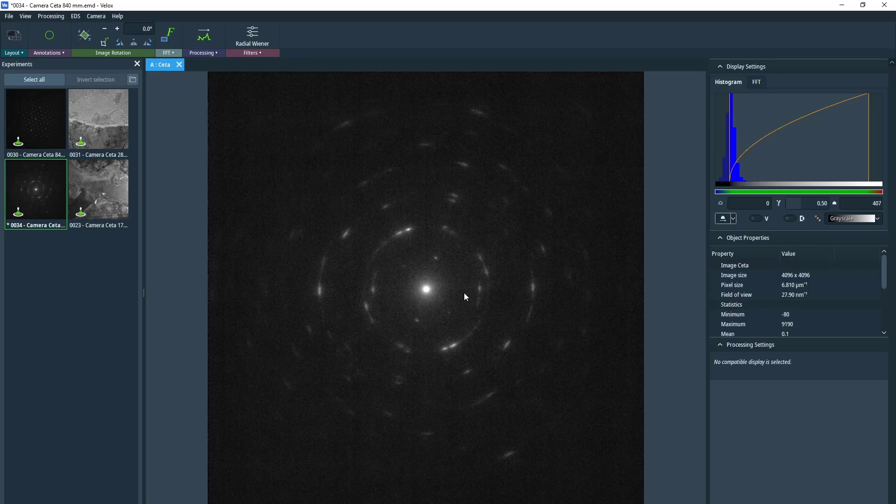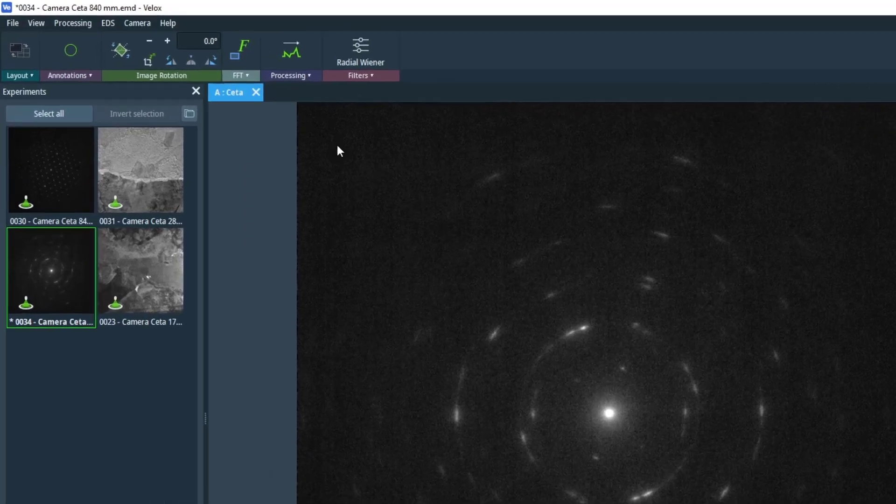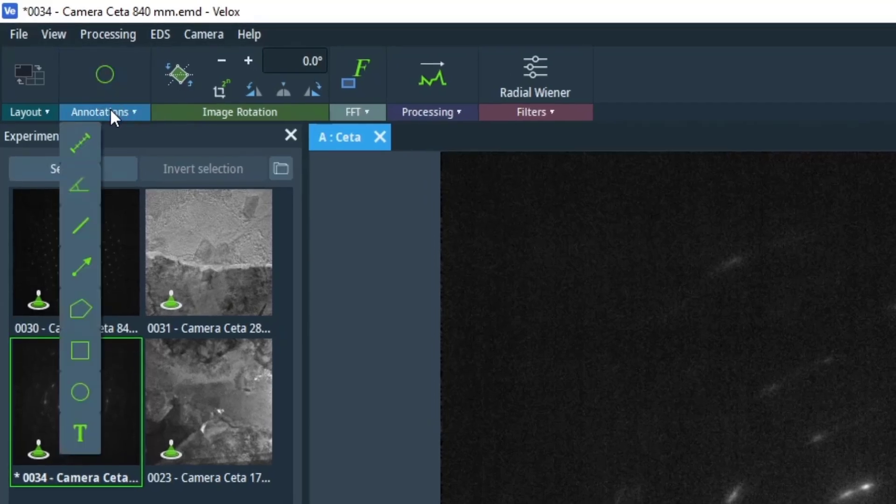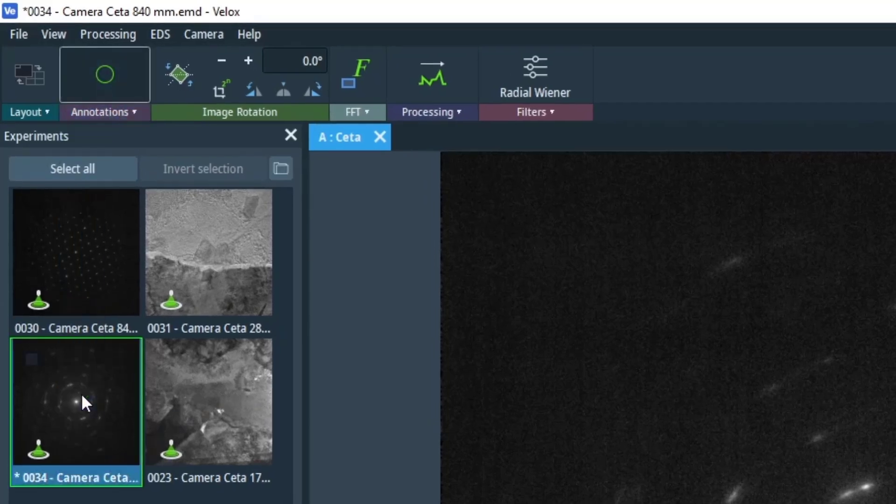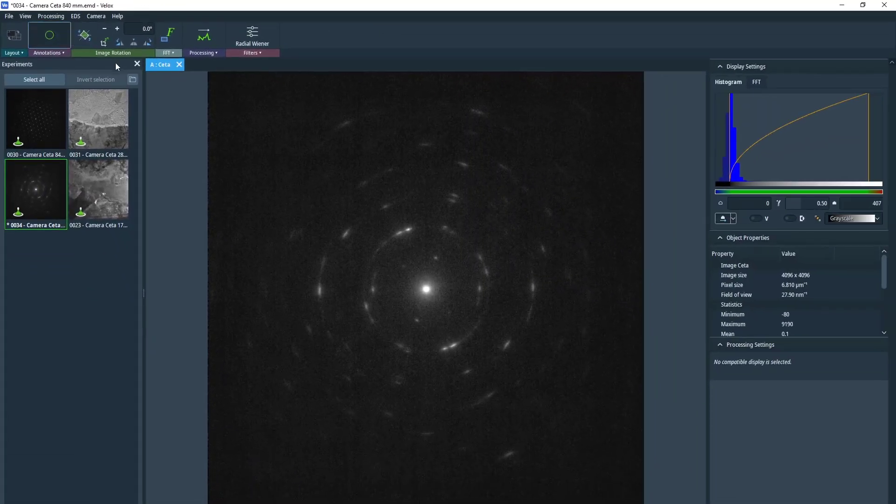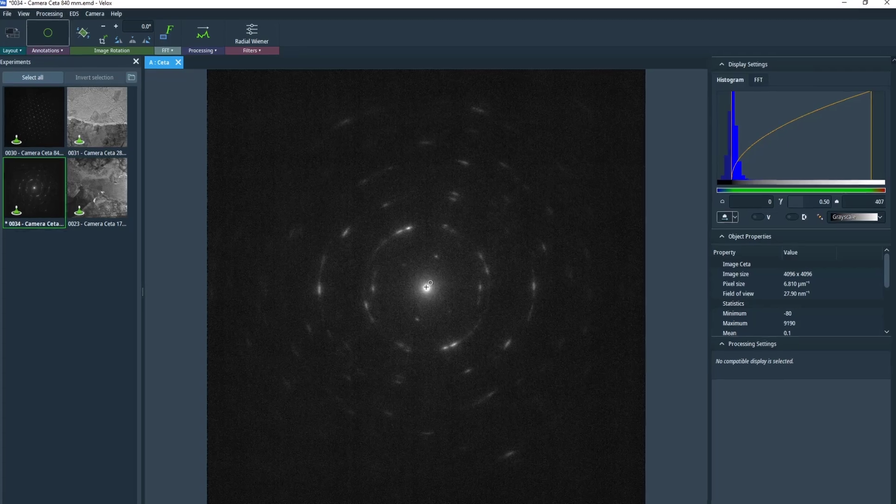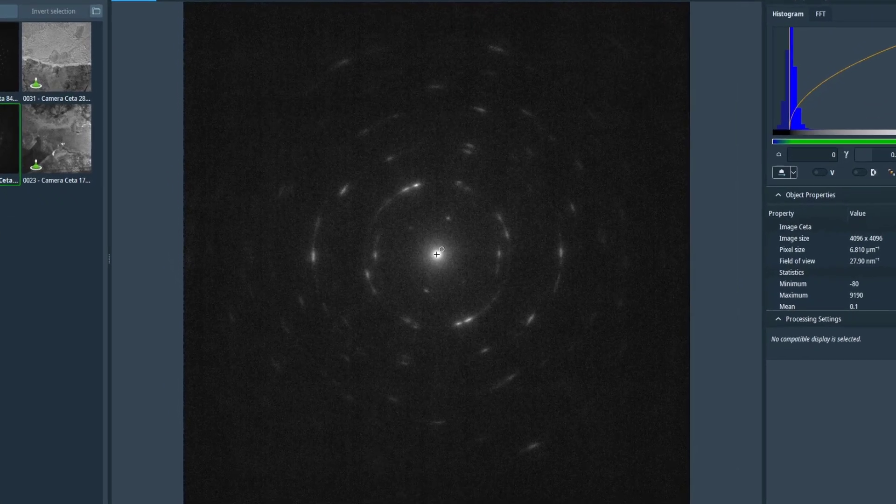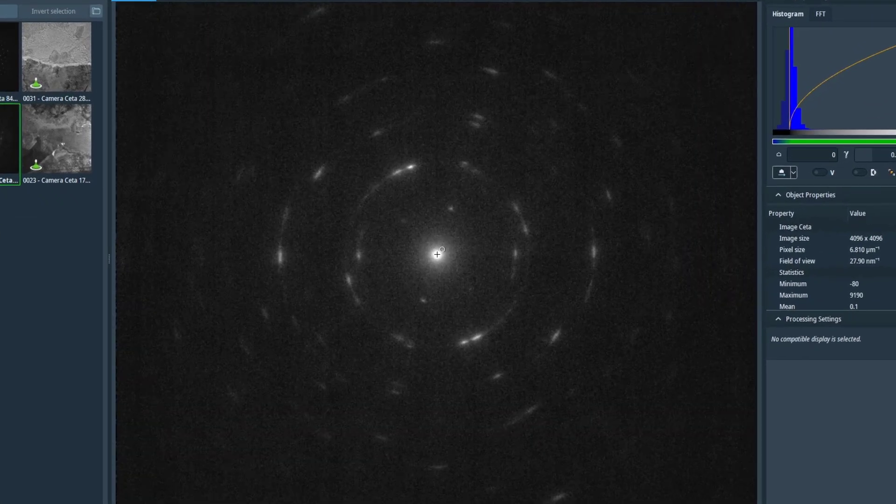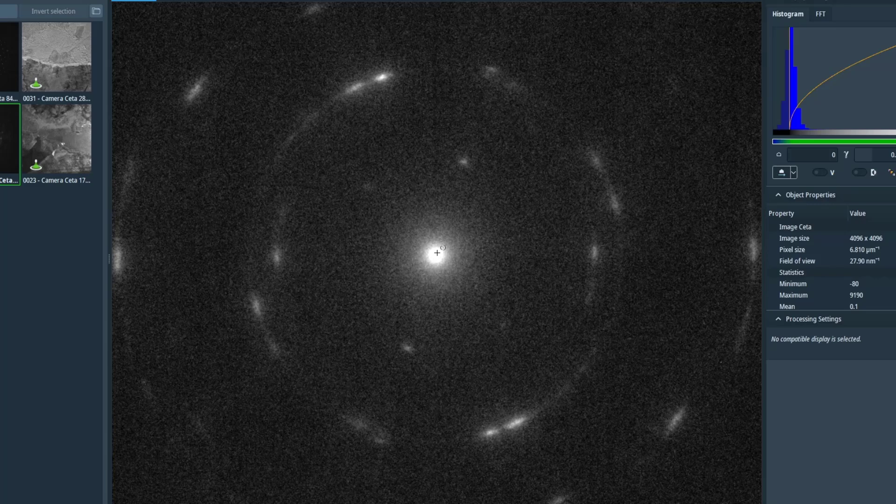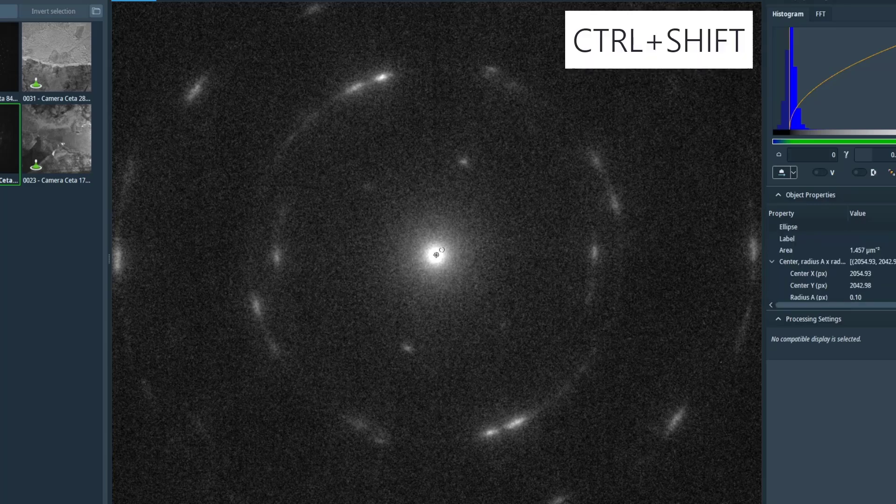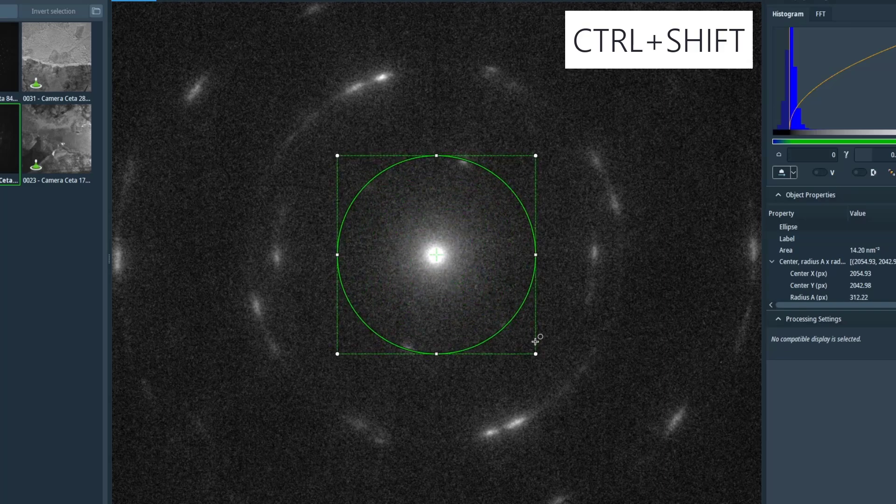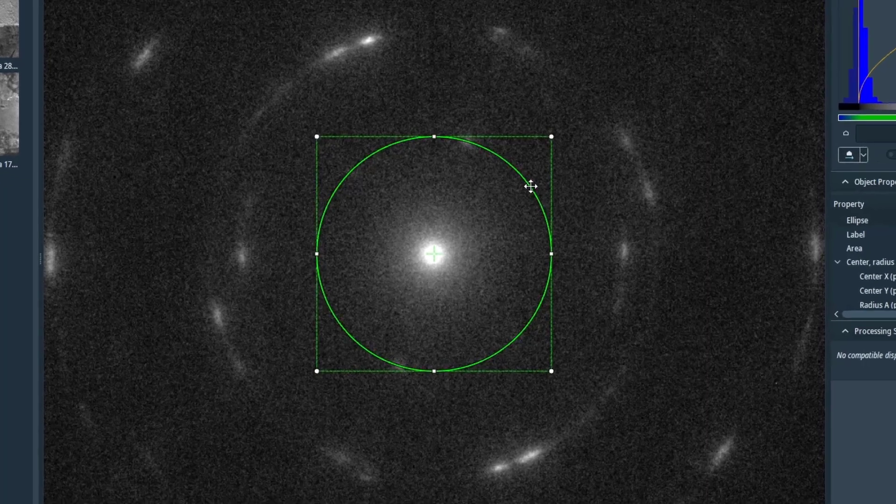Here is our ring pattern that we'll be using. The way that I like to do this is to use the circle annotation in VELOX and then measure what the radius of the circle is, because this is more accurate than doing measurements from the central spot out to these other spots. We want to try to center ourselves by zooming and using the scroll, and then if we hold Ctrl and Shift and left click on our mouse, we'll create a perfect circle from the center.